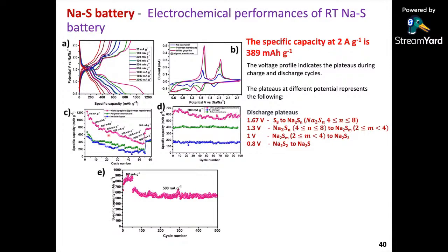So we have done this cyclic stability as well as capacity measurement, and the blue one is without any interlayer, and you can see the performance. Even in 50 cycles it drops from 500 milliampere hour per gram to very close to 100. Whereas when we use the polymer membrane only, you can see that there is an enhancement, mainly because of the enhanced diffusivity that has been obtained with the polymer membrane. But when we use this white graphite, the boron nitride traps the polysulfides, and the capacity has increased considerably from very close to 650 to 1100 milliampere hour per gram, and the fading also you can see